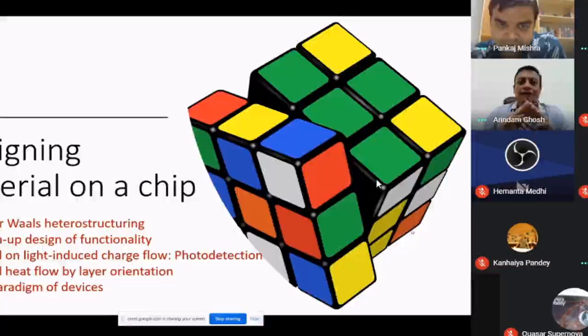So let me, in a very quick point here, first of all, in order to know the angle, it turns out that in case of MoS2, there is a very easy way of doing it. You look at the angles which are 60 degrees corners, and those edges turn out to be zigzag edges. Then you take two of those zigzag edges and you put them together. There are continuum mechanical calculations as well as experiment, which show that when you get exact 60 degrees in a twisted molybdenum disulfide layer, those edges are zigzag edges.